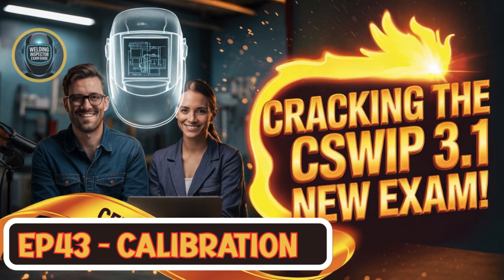Okay. Looking more specifically, typical tolerances you might see required are welding current plus or minus 2.5%, arc voltage plus or minus 5%, wire feed speed, plus or minus 2.5%. Gas flow rate is usually a bit looser, maybe plus or minus 20%. 20% for gas.